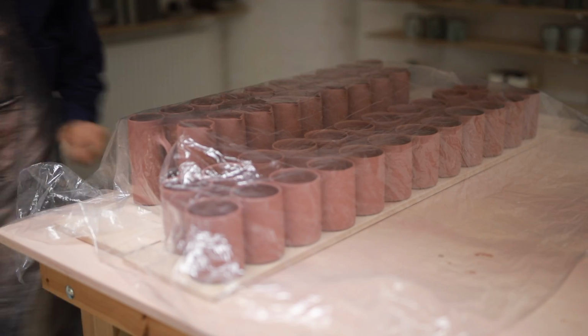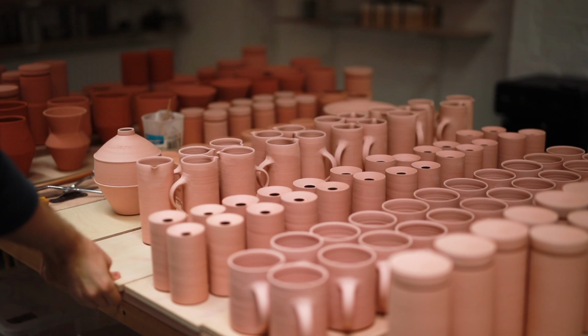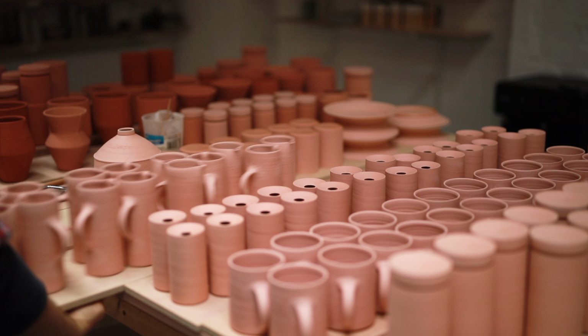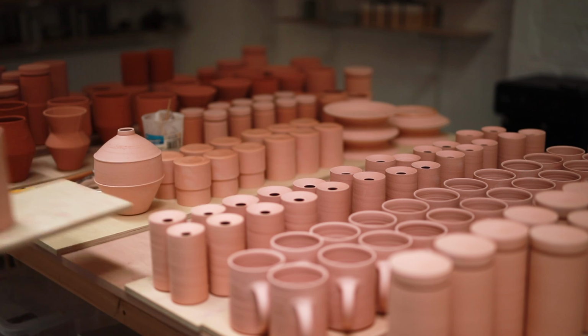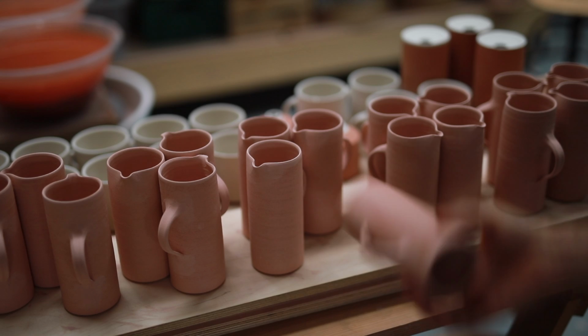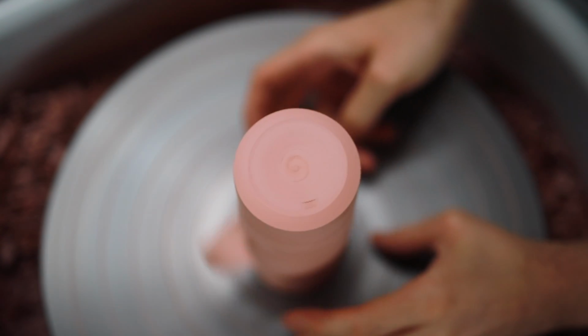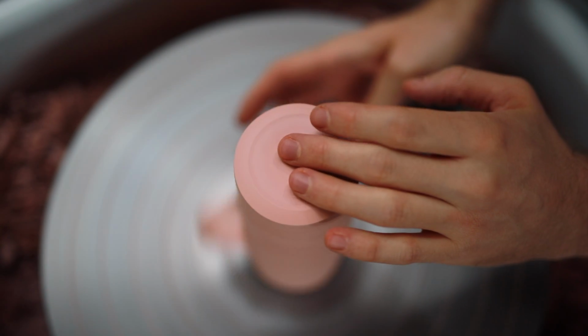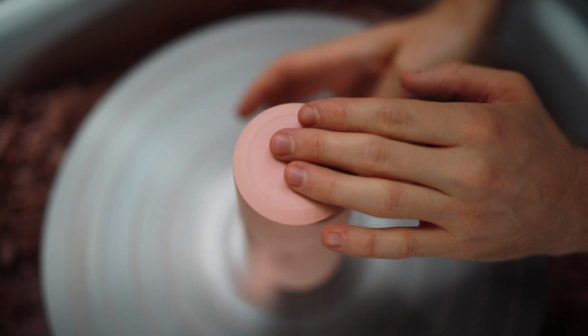Sadly, the only part of this process I forgot to film was the bisque firing, so you'll have to ignore that, and I'll try and capture it next time. So these jugs you're seeing now have actually been fired in my electric kiln up to 1000 degrees centigrade, a process which turns the clay from a material that is clay into a material that's ceramic, and very porous.